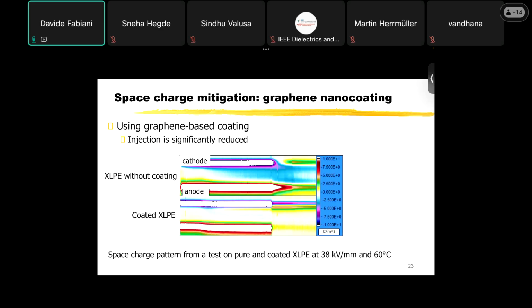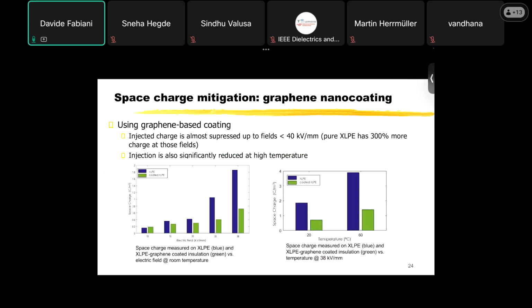As you can see here, this is without any coating, and you see a lot of accumulation, injection of negative charge. By applying a coating, this negative charge is significantly reduced at quite high field and temperature. And this is also evident looking at this plot, where you see that without a coating, we see a huge increase of the space charge as the electric field increases. While if we have this coating that prevents space charge injection, you see that it is really reduced several times. And also at high temperature, increasing the temperature, you can see that without coating, we have a big increase of the space charge accumulation, while with the coating, the space charge accumulation is very much smaller.